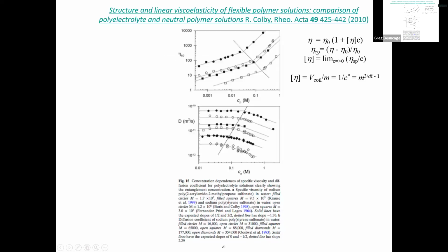Anyway, so the intrinsic is going to be, what would be that coil concentration within the coil as the concentration of the system goes to 0, because that would change a little bit with concentration. So basically, let the concentration go to 0, take that thing divided by concentration, you get this intrinsic, which would be this actual coil, 1 over the coil C star thing, right? 1 over C star would be this thing. That's kind of how, in a nutshell, this viscosity thing works.